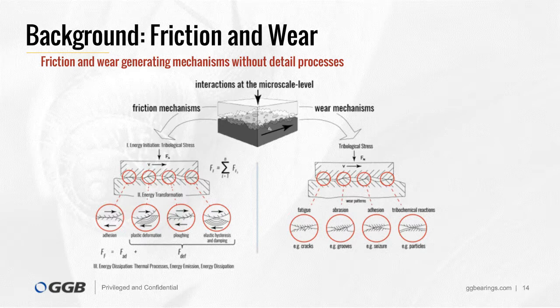In tribology, we distinguish 4 main friction and 4 main wear mechanisms. The friction mechanisms are adhesion, plastic deformation, plowing, and elastic hysteresis and damping. The adhesive friction component is a result of the formation and destruction of adhesive bonds within the real contact area. The 3 other mechanisms are based on a deforming interaction of asperities.